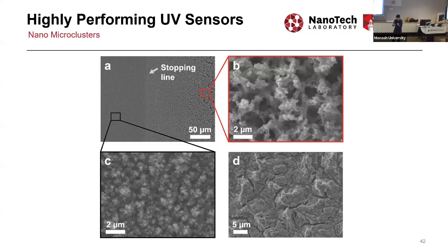But back then, we did the literature search to make sure that there was novelty involved. We couldn't find a film, but there were nanowires or nanorods growing on the surface, and then they put a droplet, and these bend into each other and create those patterns, yes. And then based on the distance between the nanowires, they bend towards the neighbor one or bend towards this one, yes. Thank you.